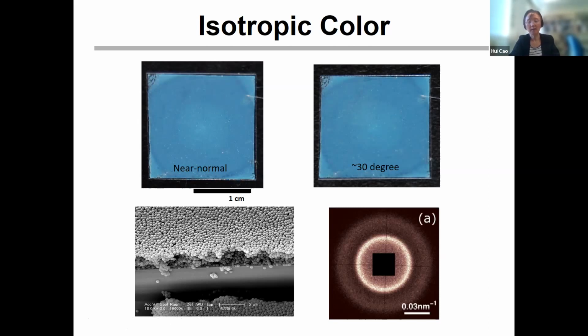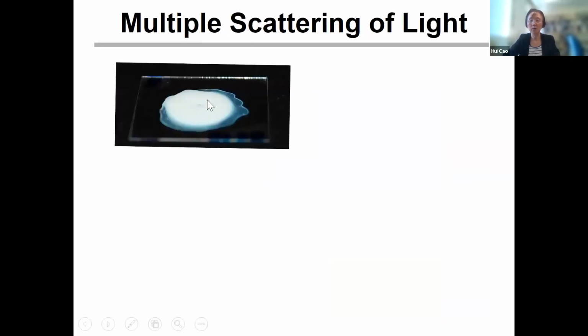So we say, okay, that's great. Maybe we can use this to get a very large scale paint, right? To really paint using this kind of structures. It's pretty easy to make. But if we want to paint a wall, we cannot do spin coating. So what we typically do is drop casting, right? We have this solution, we drop it on the substrate and then let it dry.